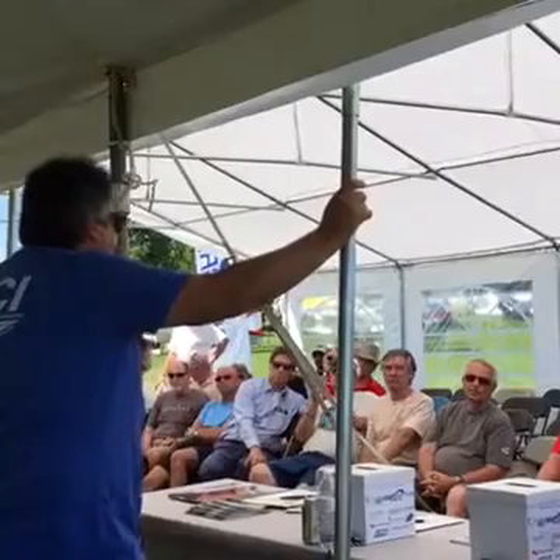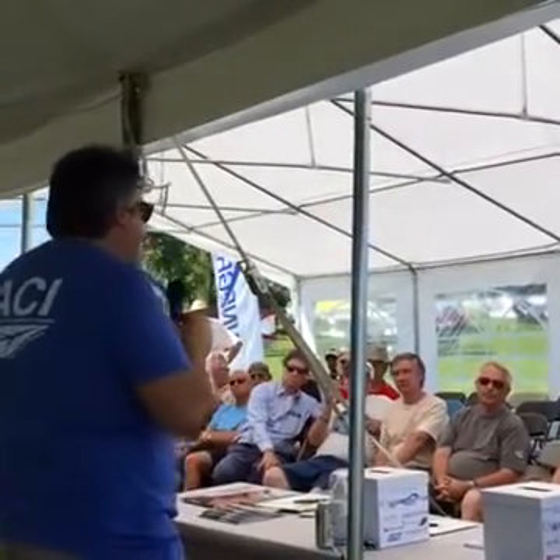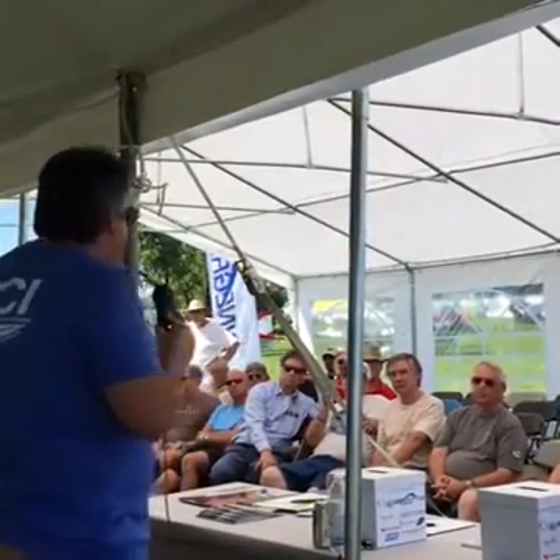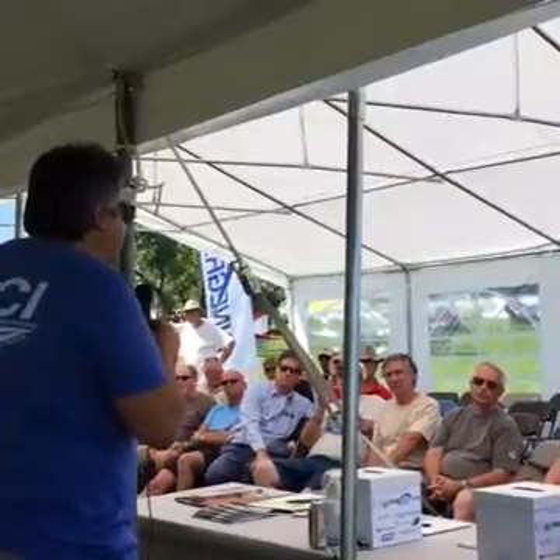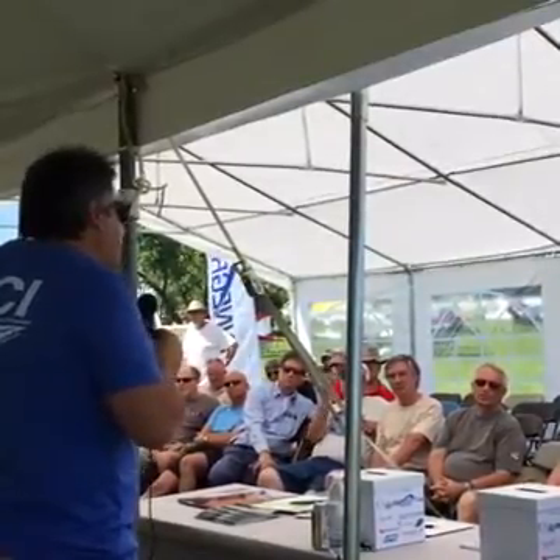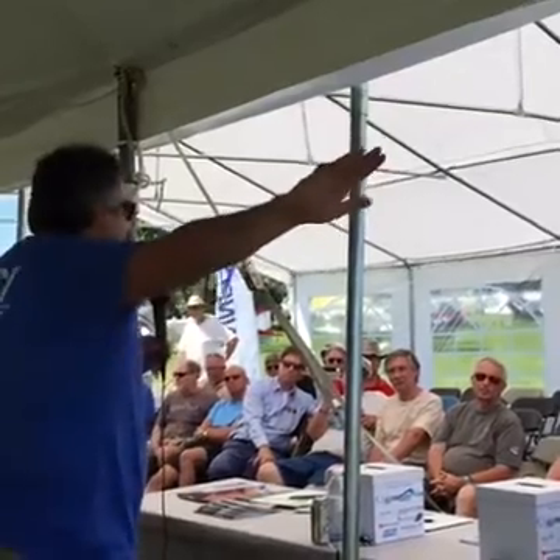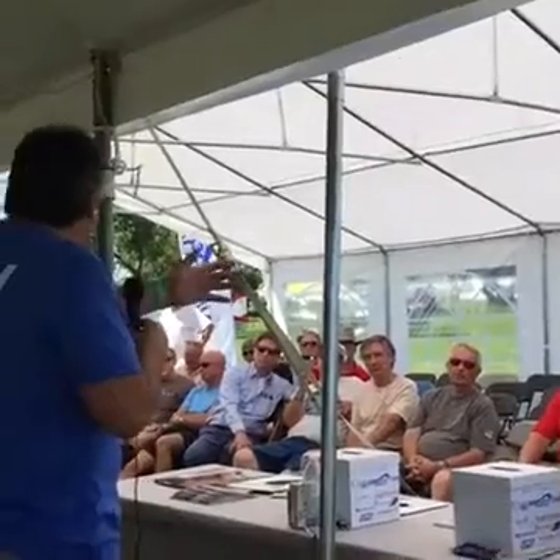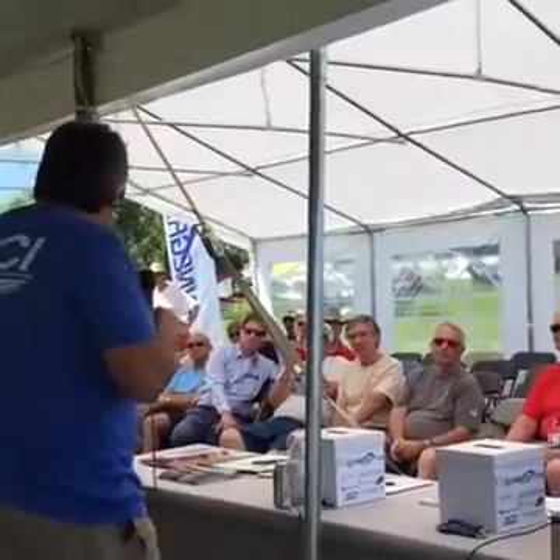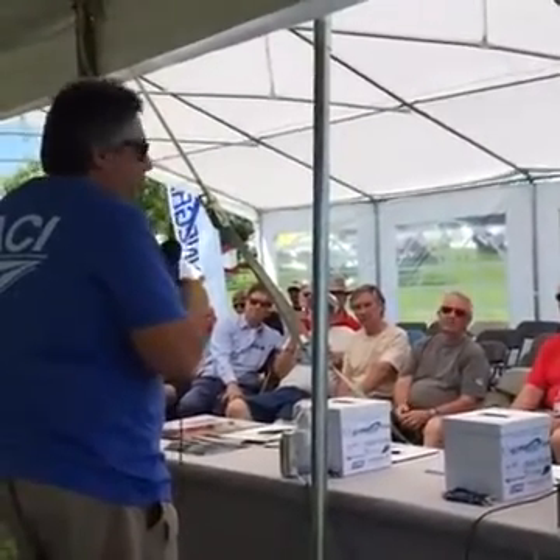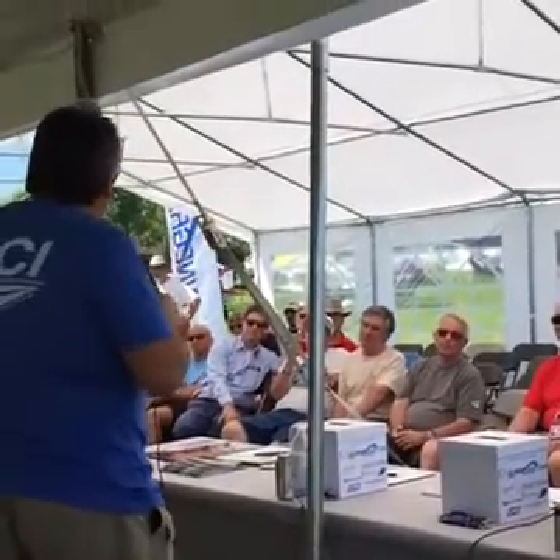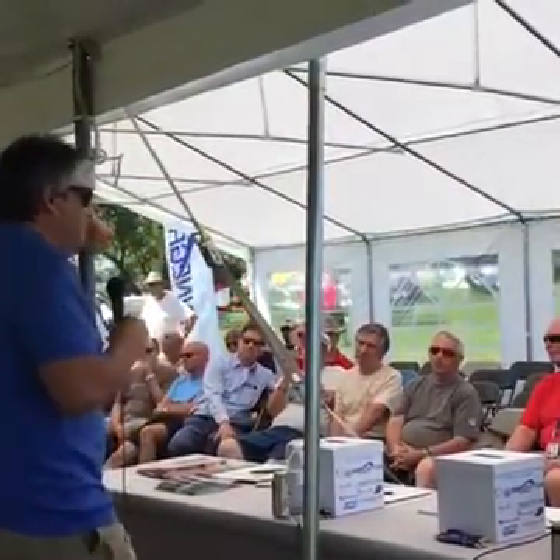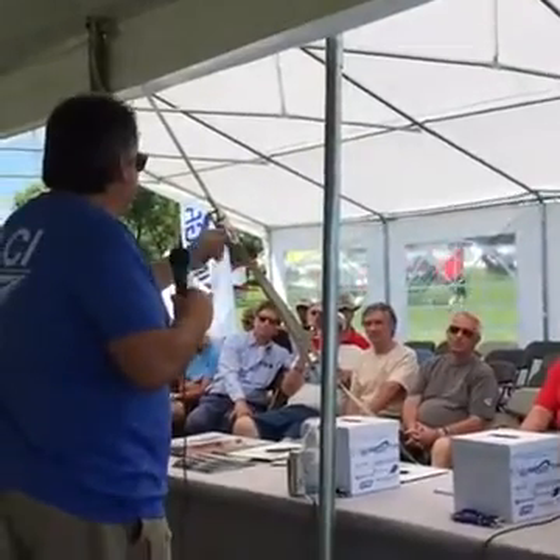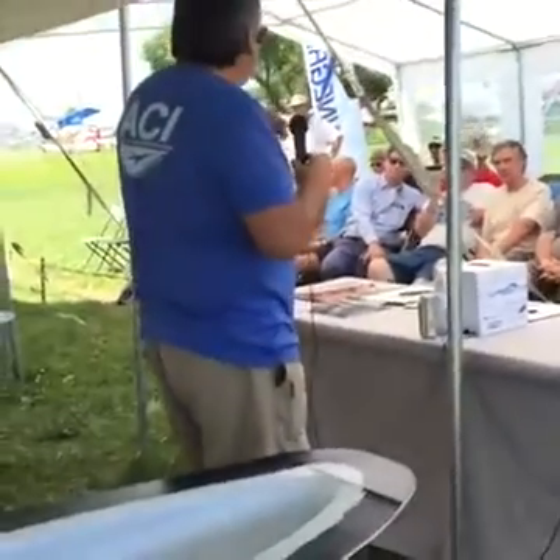What we typically tell people is if you want to get a very glossy surface in an application like this, when you're done infusing it, let it gel up. It's going to gel up in about 45 minutes to an hour. After it gels, take it outside and set it in the sun. That will help thermal cure. Most people, you guys are home builders, you don't have big ovens at your house where you can move this thing into. But if you do that, you'll get a really nice, shiny, glossy surface on the top of it. And that way all your shrinkage does occur inside the mold as well. So that's what we recommend this week.